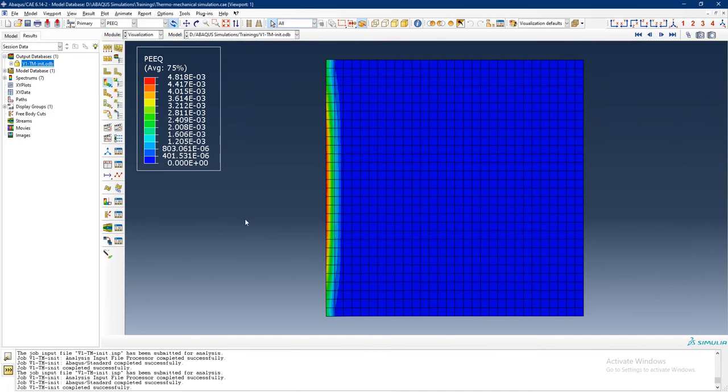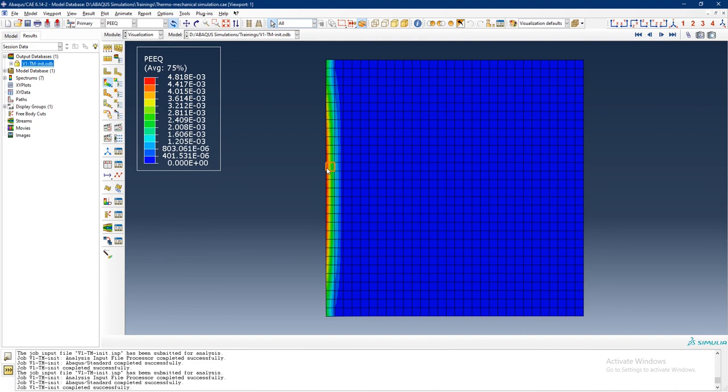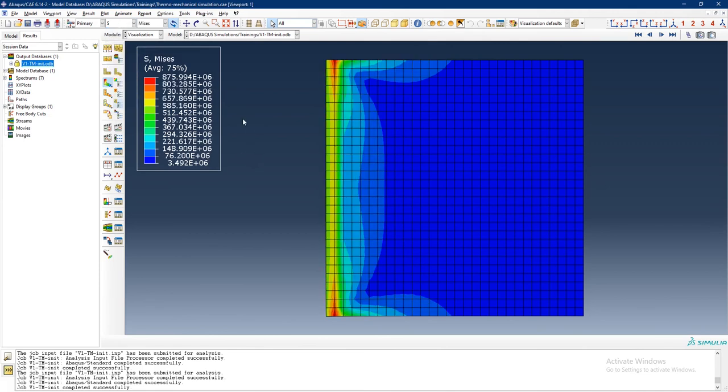When due to heat the part is expanding, this is the part where it yields. This is the response: we only applied thermal load but we are getting mechanical responses. We can also see stresses. It is easier to see stresses in x direction where on the surfaces we see very less stresses, but as we go deep down there are tensile stresses and compressive stresses around the corners.